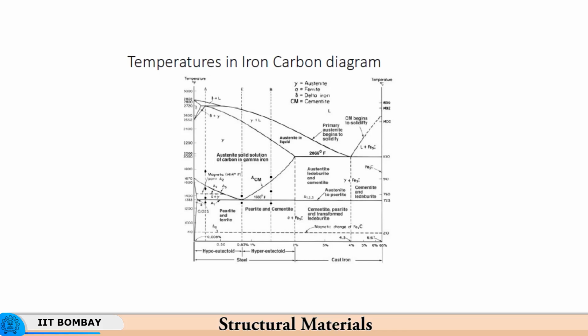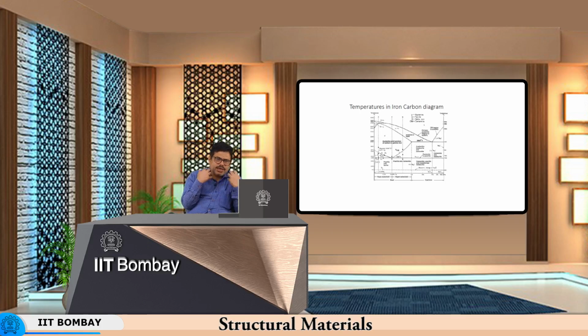Normally what people do is, if they want to deform the material, if you want to generate a large dislocation density in the material, they heat it to the gamma phase, that is a single phase, and then they deform the material. So, you do not have to go to very high temperatures, you can go right up to here, for example. So, the temperatures can be relatively smaller at 800 degrees centigrade or so. You can heat the material to the austenitizing range, meaning to austenite temperature, get a single phase and deform the material.